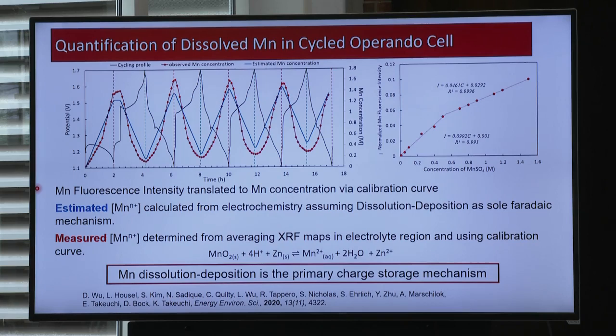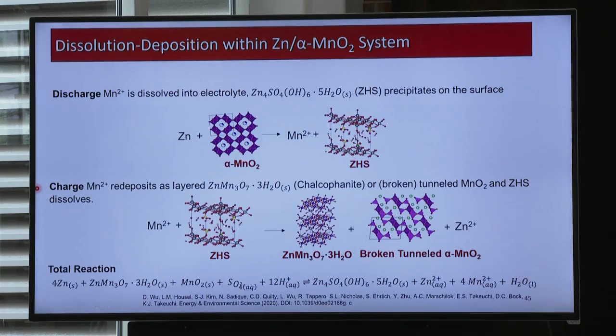So what's happening here is on reduction of the manganese 4 and manganese 3, when it's reduced to manganese 2, the manganese plus 2 goes into the aqueous electrolyte layer as a hydrated cation and then remains in the electrolyte layer until the charge step, where the manganese 2 is oxidized and then redeposits on the cathode. And it's this mechanism that helps rationalize why there are so many disparate reports in the literature that, in fact, it is changing phase, it is changing structure. If you look at things in isolation, it's hard, if not impossible, to see the whole sequence taking place simultaneously. So this gives you a picture at the molecular level of what's happening.